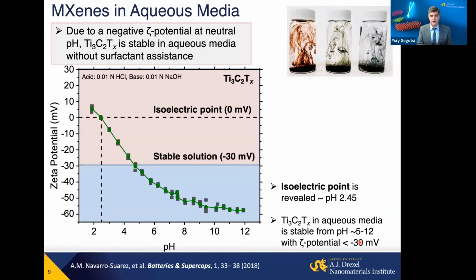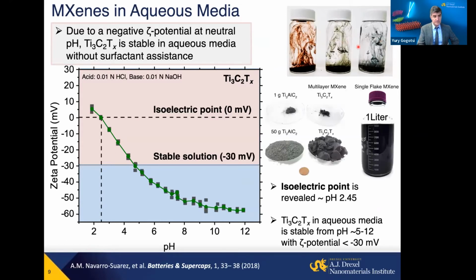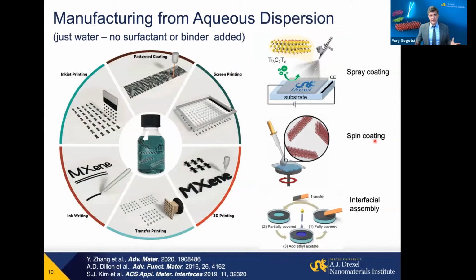Why can we work with these materials using aqueous dispersion? What is very, very important for actually sustainable processing and manufacturing here, because there is a high negative charge on the surface. Zeta potential of MXene typically ranges between -30 and -80 millivolt at pH close to neutral, allowing us to very easily disperse these particles in colloidal solutions. And starting with the ceramics, we end up with this etched material, disperse it in water, and we get this colloid of two-dimensional particles. If we have a colloidal solution in water, we can use any known processing technique to produce films, produce patterns. We can do 2D printing, 3D printing, spin coating, spray coating, dip coating, you name it here.